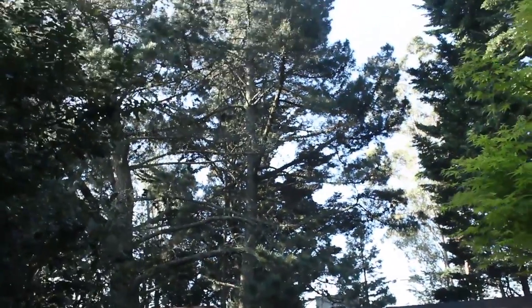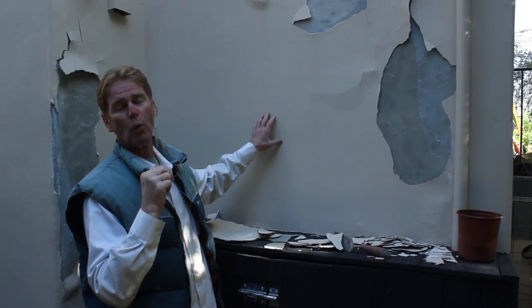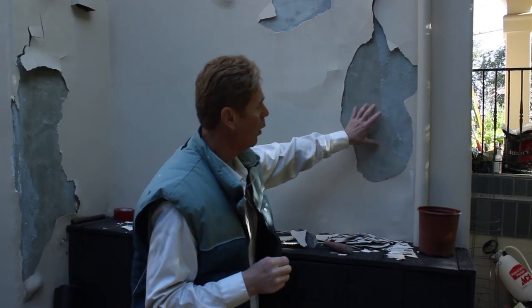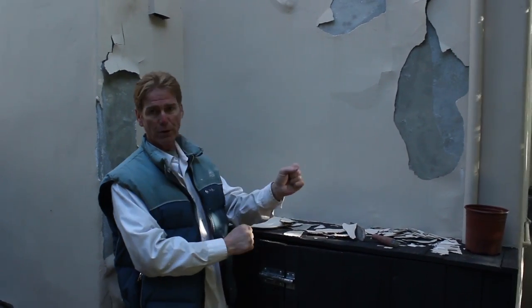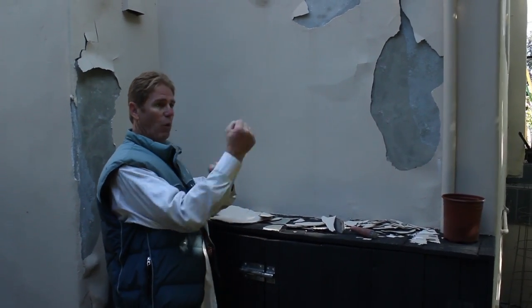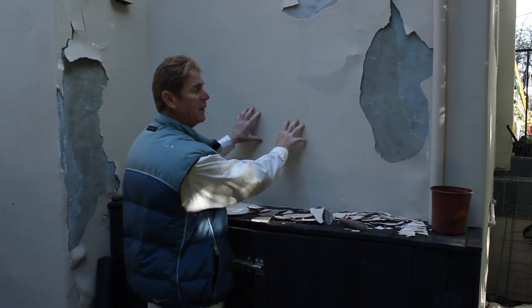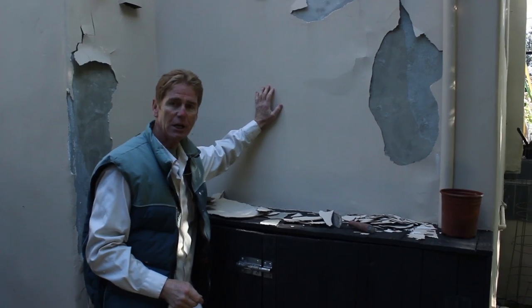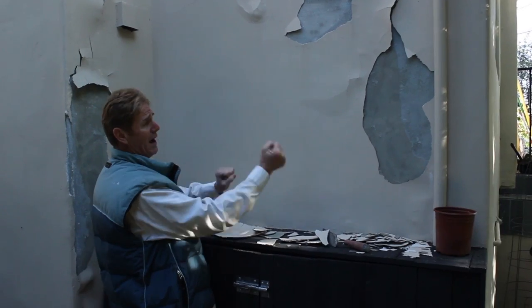Here's something weird but it's a fact - that tree over there emits a yellow type of dust sometimes, and that dust goes all over. I know because I've got the same tree and that dust covers everything. So when they did this wall, two things caused the separation from the base coat: number one it's too smooth, and number two whoever did this area didn't have a water hose. You wet the wall and wash the dust off, because nothing adheres to a dusty surface. They put it on dry.